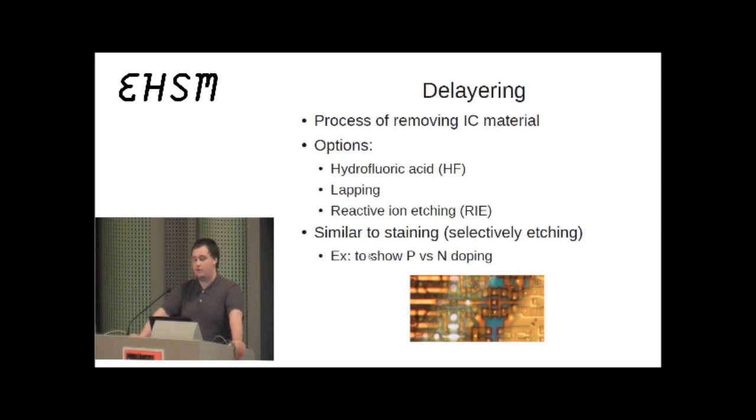And kind of in a related field is what we call staining, which is basically selective etching. So an example of this is you've probably heard of ROMs, the read-only memories, for example, in a game cartridge. The earliest ones would use metal to connect the positive and negative rails to each of the little data bits, and so you could actually read these out with a microscope. But as time went on, partially for manufacturing reasons and partly to make reverse engineering harder, they switched to using an implant method, for example, which is where you basically diffuse different negative and positive impurities into the chip to make different conductive paths. Oftentimes, those are very difficult to read optically. However, because they are slightly more positive or negative than the other, you can use certain chemical techniques that will favor etching positive or negative areas, and you will get a kind of outlined form, which might not be super easy to read, but if you use certain microscopy techniques, you can pick it out and read it optically.